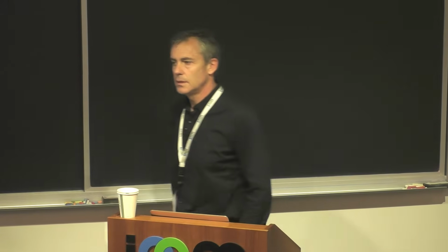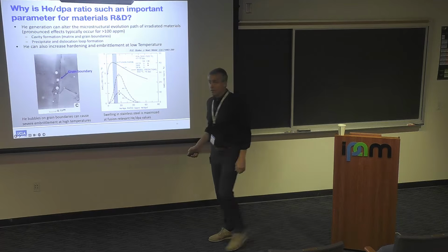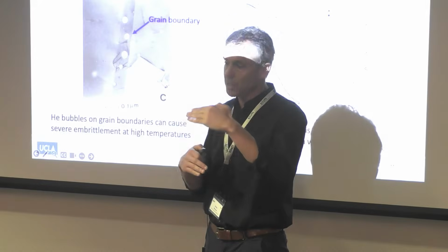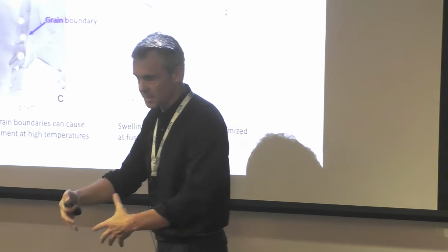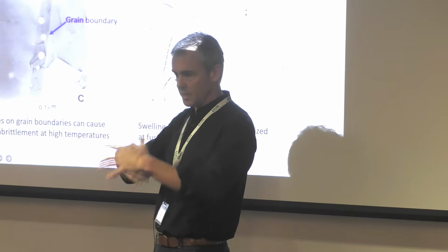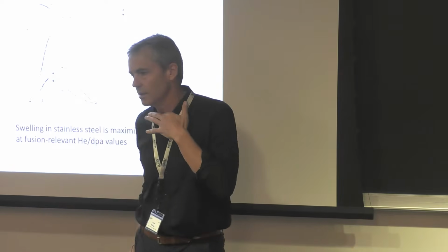But the helium bubble creation, I mean, that's all based on simulations? No. Yeah, but under fusion power plant conditions, I mean, no one knows, right? Yeah, no one knows. These are emulated conditions, experiments with similar conditions. I'm going to show you later how we try to design experiments where the ratio of displacements to helium production is the same as in a fusion reactor. We inject helium at the same time as we inject displacements, and we see their coevolution, as you would presumably have in a fusion reactor.